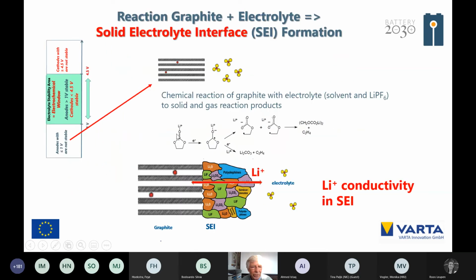So what is going on if you are outside of that electrochemical window? The graphite, the lithiated graphite, is reacting with the electrolyte. And that is a chemical, only a chemical, not an electrochemical reaction of the graphite with the electrolyte. And solids are formed, lithium carbonate, that one, and also gases are formed during the chemical reaction between the graphite and the electrolyte. And that chemical reaction builds up a so-called solid electrolyte interface. The good thing is that the SEI is conductive for lithium ions. So the lithium ions could go through that layer.